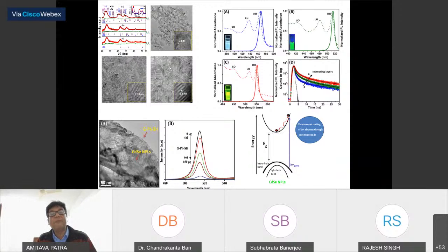So this is the 3 layer, 4 layer, 5 layer structure, which we want to confirm from the X-ray, and this structure is 1.25 nanometer, 1.5, 1 nanometer. I will not go into this detail. This is the 3 layer, 4 layer, and 5 layer system. So the whole relaxation process we have seen can be controlled if you make a heterostructure, because I want to extract that electron from the 2D structure, otherwise you cannot extract.